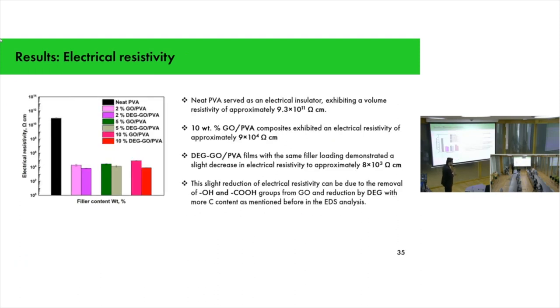Whereas if you talk about electrical resistivity, neat PVA served as an electrical insulator, with a volume resistivity of 9.3 times 10 to the power 11 ohm centimeter. Our 10 weight percent graphene oxide PVA system has an electrical resistivity of almost 9 times 10 to the power 4. But if you reduce the filler, you see that there is a slight decrease in electrical resistivity to approximately 8 times 10 to the power 3 ohm centimeter. This reduction of electrical resistivity can be due to the removal of hydroxyl and carboxyl groups from graphene oxide in the reduction process, leaving more carbon content, as mentioned before in the EDS analysis.